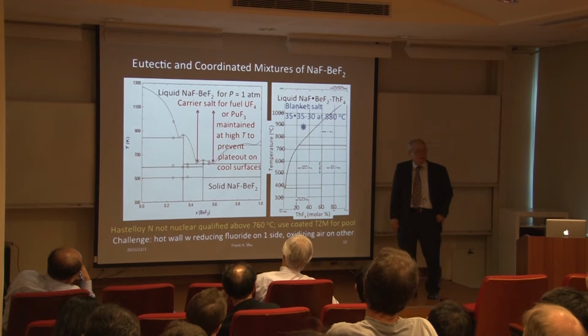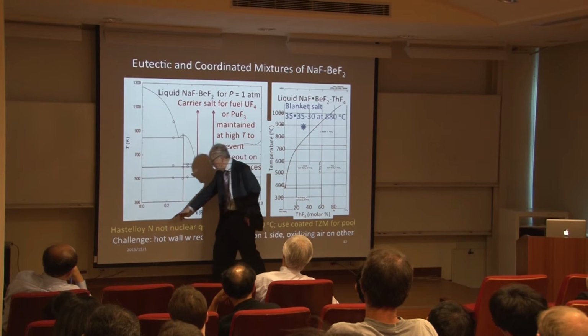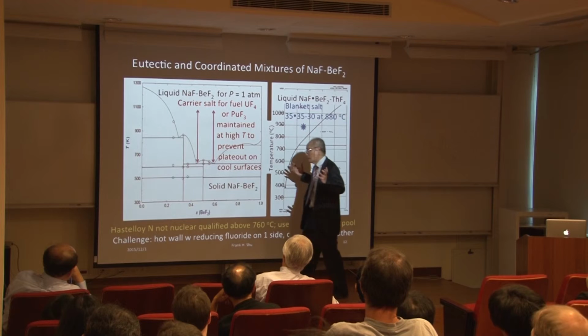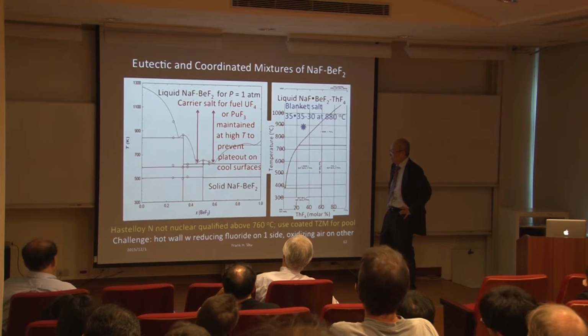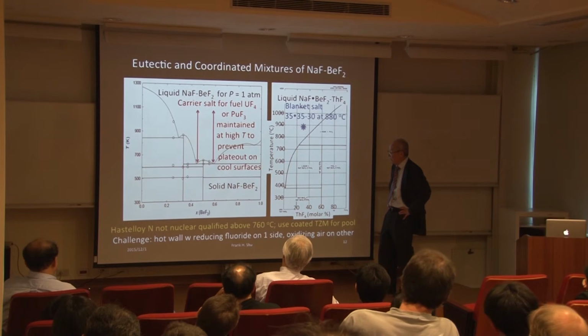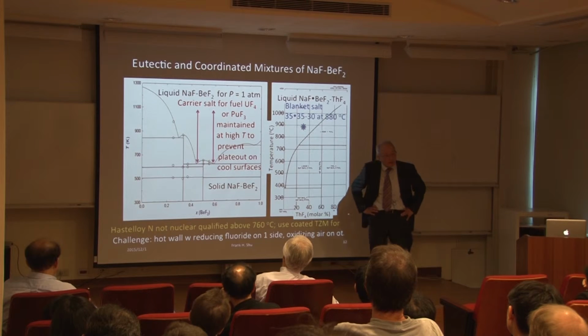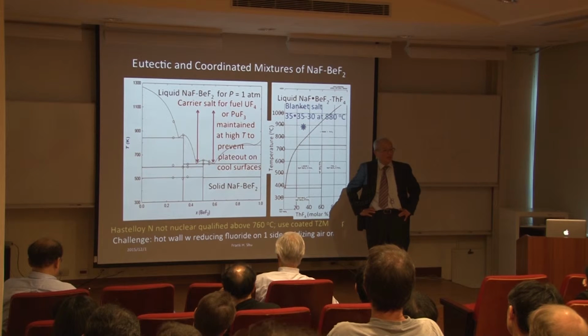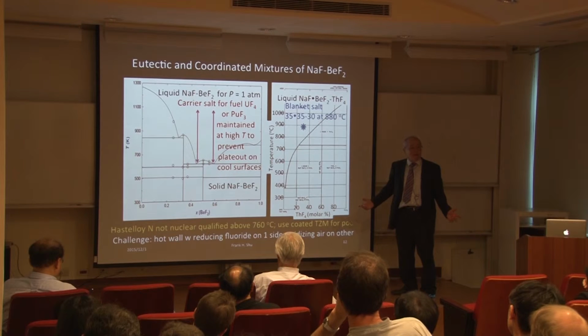How many metals can withstand 880 C and not be corroded by the salt? And the answer is, conventionally, everyone thinks it's Hastelloy-N. This is what Oak Ridge invented to contain lithium beryllium fluoride. But it's only nuclear qualified for 760 degrees. Doesn't mean it can't handle more than 760 degrees, but then you have a long fight with the regulatory agency ahead of you. So you can't use the thing that everybody says you should use.